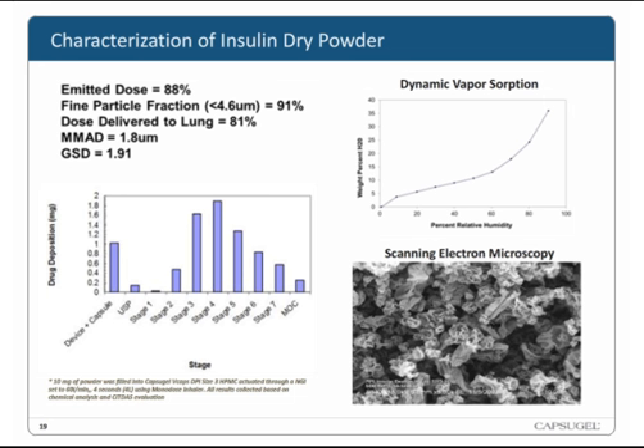We also like to look at dynamic vapor sorption and how that relates to the glass transition temperature. And this is used to define the storage condition, because if we take on too much water, we're going to have stability issues both with particle-particle agglomeration as well as enabling mobility of the active in the particle, which can allow for unfolding or even aggregation in the dry powder state. So we use this to define the storage conditions, and we typically like to be less than 3 weight % water, and so we use that to define the less than 10% RH.